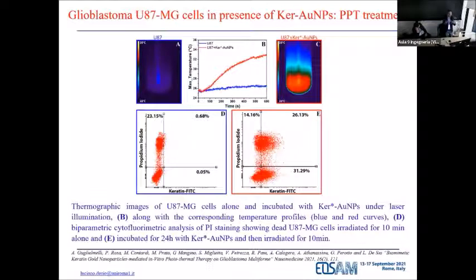We don't care about the temperature we're able to reach. But still, the reduction in viability is not very high. It's about 30%. It's not a lot. That's why this kind of cancer cells are very hard. They cannot die very easily. That's why most likely we have increased the temperature a little bit. But here there is a limitation due to the fact that spherical gold nanoparticles do not perform very well in terms of photothermal efficiency. For this, we are looking for something better, for something a little bit more exotic, maybe.